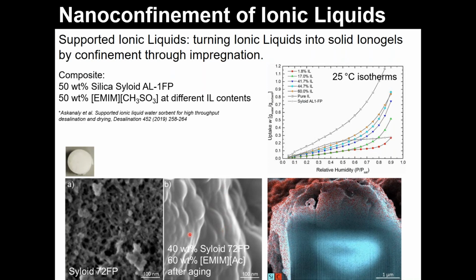Essentially, you are losing all the porosity, and you are working with a thin layer of liquid solvent, the ionic liquid. The EDX shows what I have just said. The pores are partially filled with ionic liquids, but are not actually contributing to the sorption mechanism, because at a high level of impregnation, 60%, you basically have a thin film of ionic liquid spread on the surface.